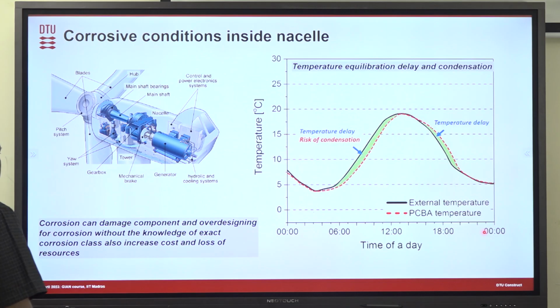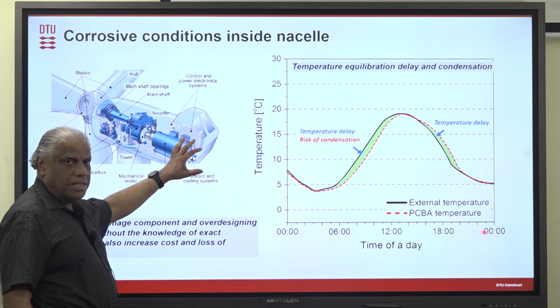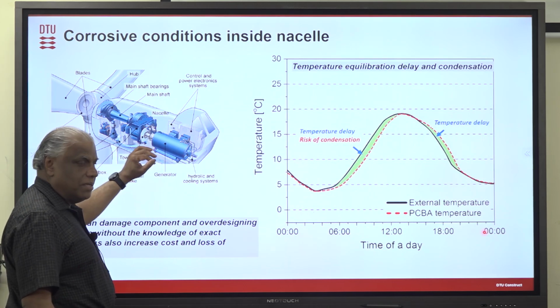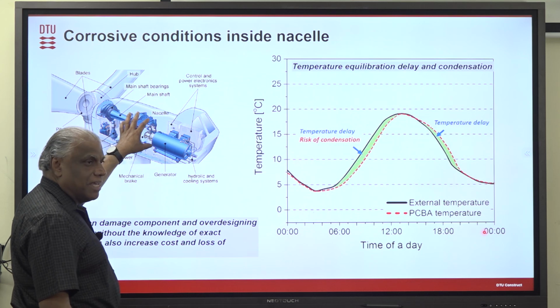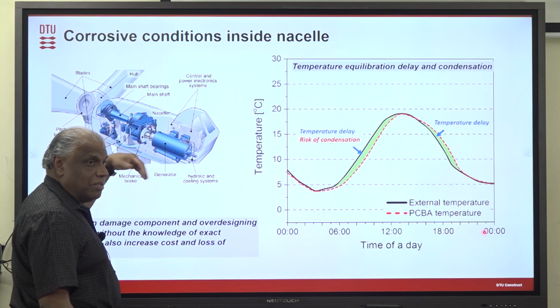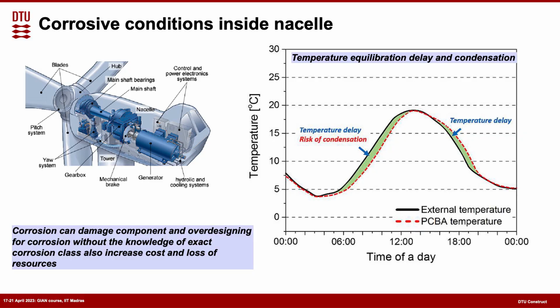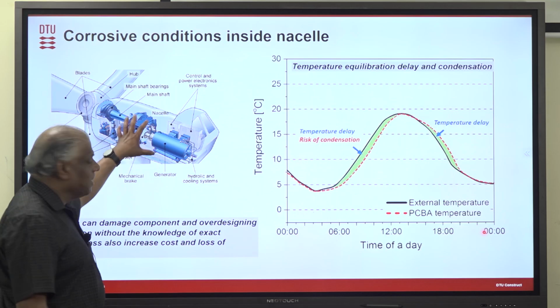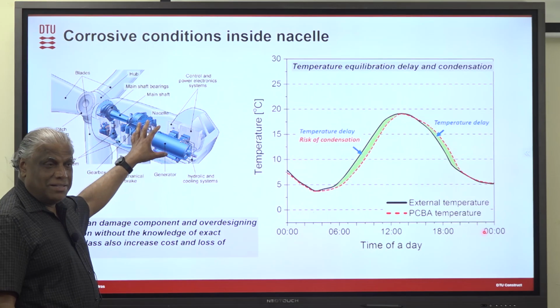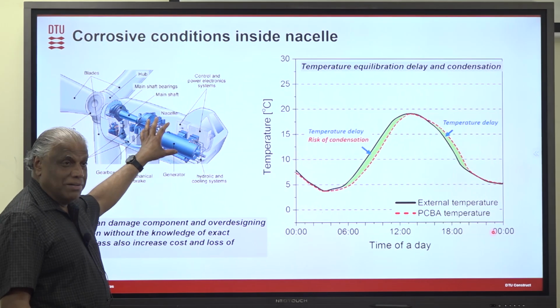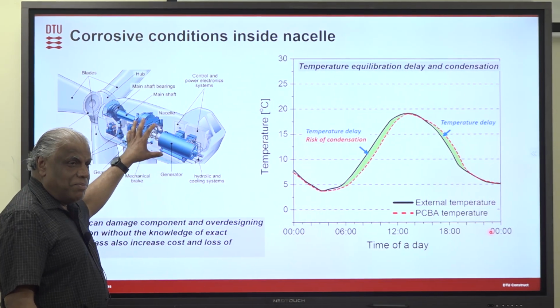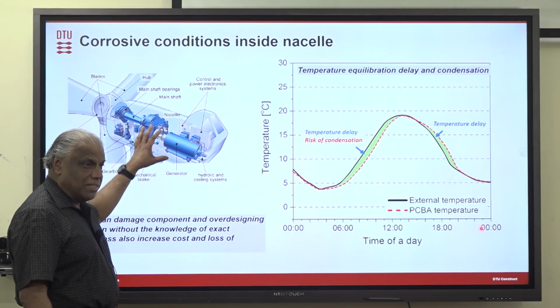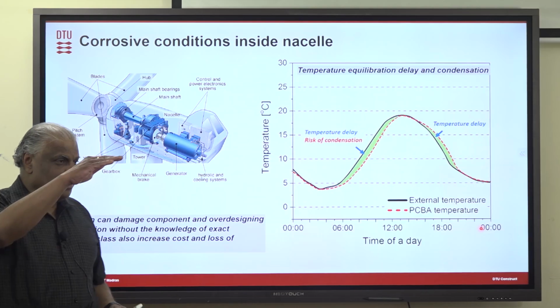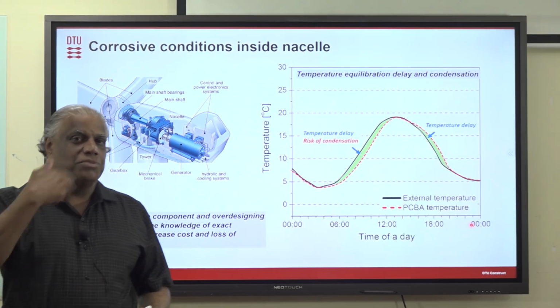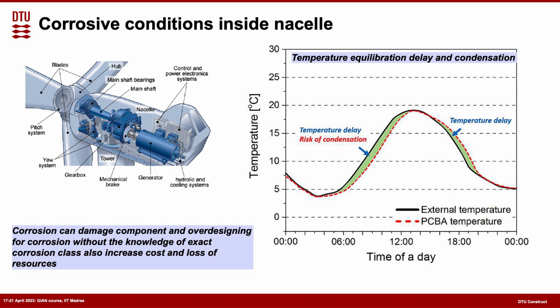As I told, the nacelle condition is quite good if the wind turbine is working, because the gearbox is producing a lot of heat. So most of the problem comes when the wind turbine is not working. When it is not working, it is very, very cold, right? You need to think that this is like a very thick metallic sample. The problem with a thick metallic sample from the corrosion point of view is that it takes time to heat up and it takes time to cool down. And this is where the atmospheric condition and the corrosion problems become more important.